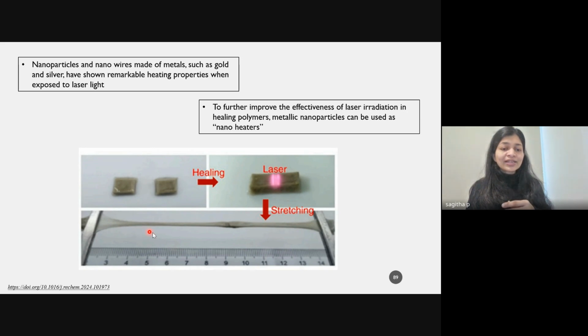And this is the material after stretching, after the healing process. What they have seen is that silver nanoparticles can provide the healing or make the healing process faster. Within 1 minute the material underwent the healing process and regenerated its normal shape. Nanoparticles and nanowires made of metals such as gold and silver have shown remarkable heating properties when exposed to laser light. To further improve the effectiveness of laser radiation in healing polymers, we can use these kinds of nanomaterials, which can provide the required energy for the healing process.